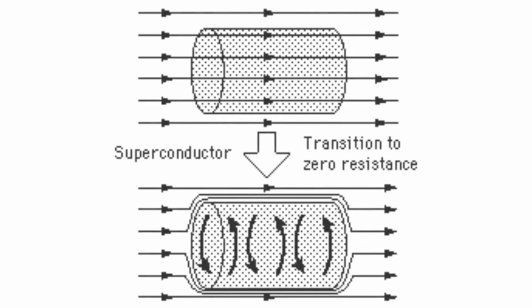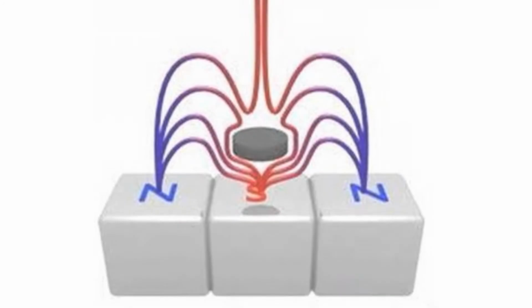As the superconductor is cooled past its Tc, it expels all magnetic fields from its interior via electrical currents on the surface. As you can see illustrated in this diagram, no field lines pass through the interior of the material, but instead bend around it. If you set up the field correctly when you transition it, then you can achieve levitation.